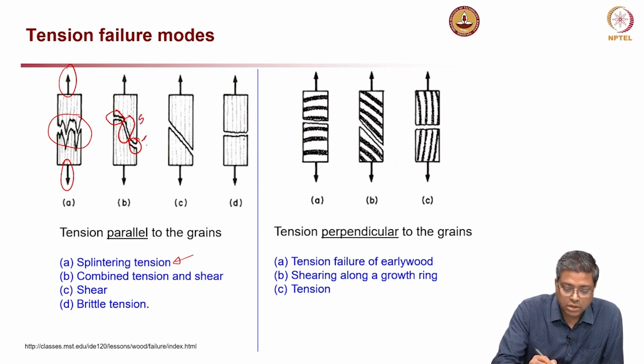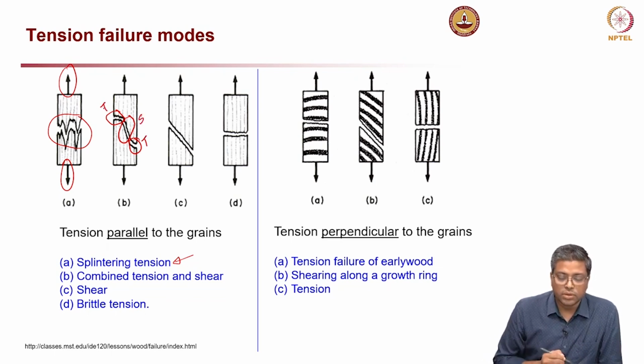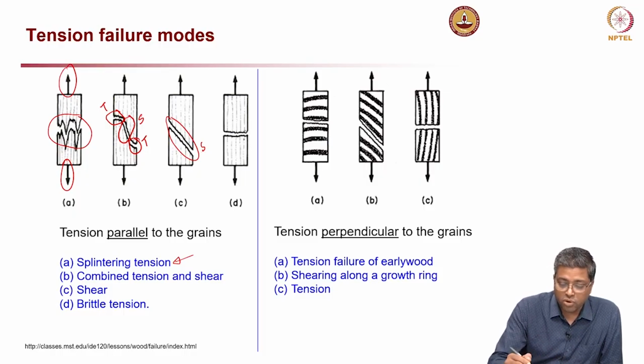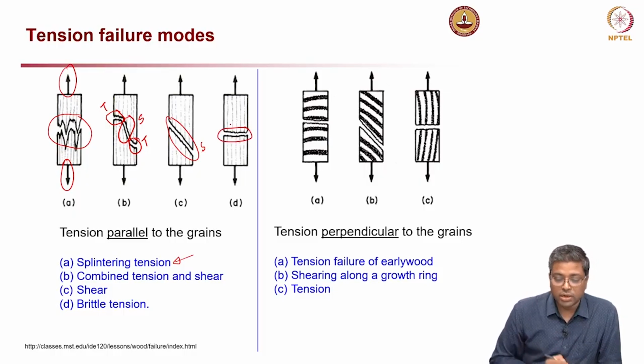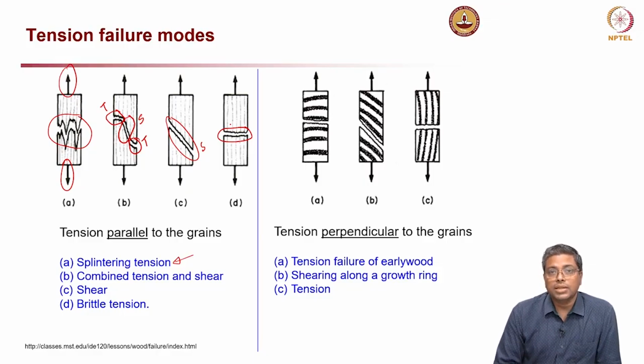So, shear, tension, tension. Now, the third case you can see is a pure shear failure. This is all shear failure. Then fourth is pure tension. So, pure tension, pure shear, splintering and a combination of tension and shear. These are the 4 different ways by which wood can fail when you apply a tension load in the direction parallel to the fibers.